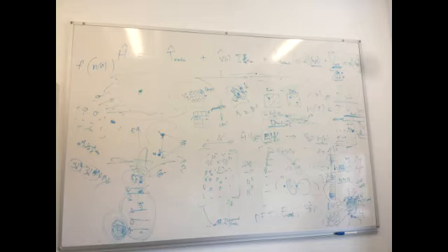So basically what molecular dynamics is, you do a DFT as we did, and DFT tells you the density. And now you give some velocity to each atom, to represent the temperature. So now you start to shake them, and if you shake it away from its stable position, this density will define the force that pushes this atom back.